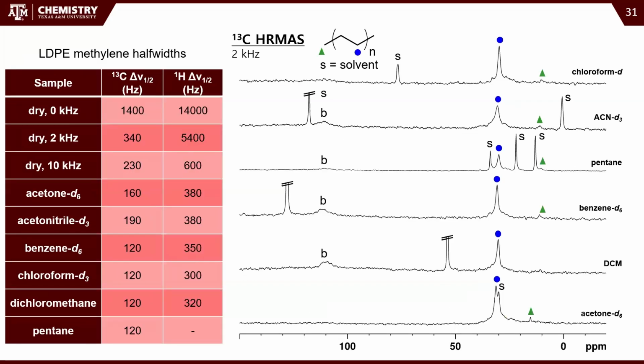And carbon NMR will get intrinsically better resolution, right? We have a larger chemical shift range, and we have much weaker, non-existent homonuclear dipolar interactions because 13C is pretty dilute, right? So we get better resolution, and you can see, again, even in the solid state, we have 230 hertz, which is much better than proton. And then with HR MAS, we see again about a 2 times increase in the resolution. So this is kind of the best tool if you want to be characterizing interesting polymers. And you can see again the ethylene chain and then the methyl groups there. And if you want to kind of close your eyes and pretend, or squint and pretend, then you can imagine these shoulders are probably the tertiary carbon branching groups. We don't know the degree of branching for this material, so we didn't investigate that at all, but there are signals of it.